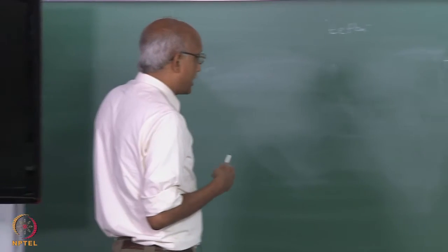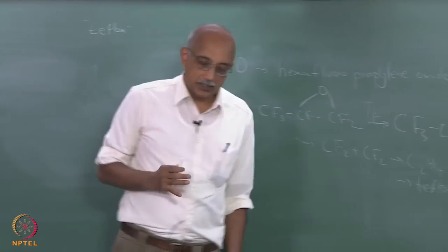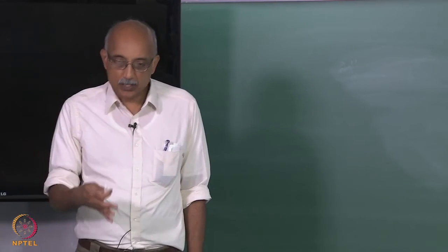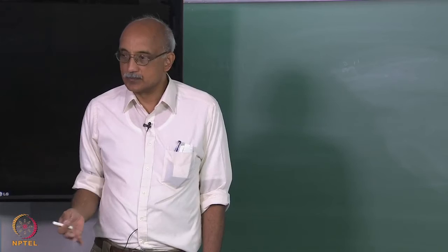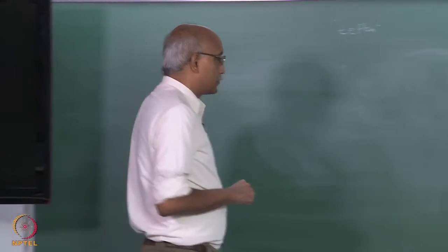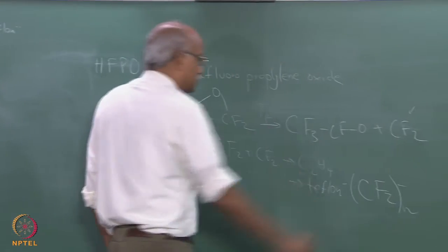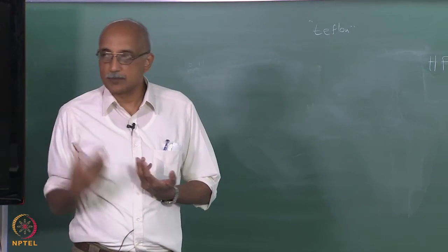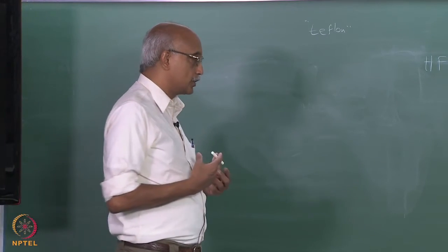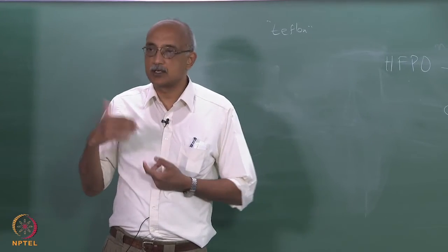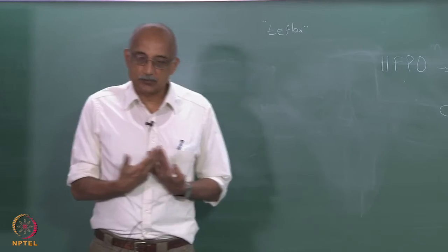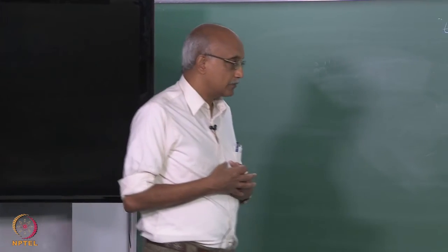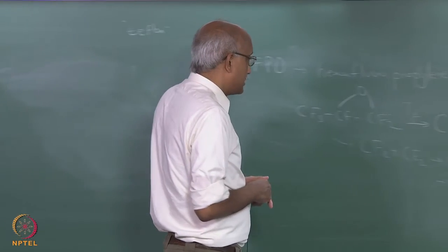So if you look at some of the challenges of making Teflon coatings, and the reason that the hot wire CVD reactor is quite advantageous for this process is that the presence of the hot wire provides your dissociation mechanism, right? That part is obvious. Now, how do you again get the CF2 to link to other CF2 molecules? You have to provide a chemically reactive environment, again with high temperatures being present, and provide also sufficient energy so that the homogeneous kinetic barriers are overcome. Because in order for a CF2 molecule to combine with a CF2 molecule in the gas phase and form a C2F4 takes energy.